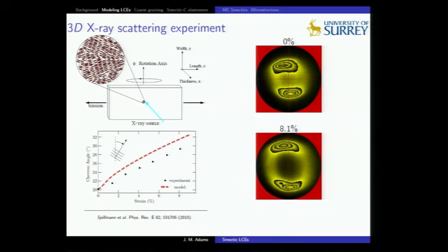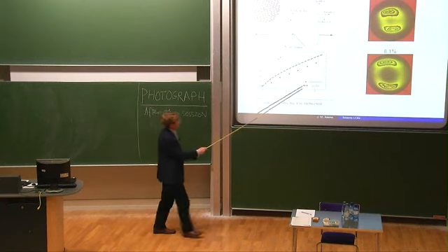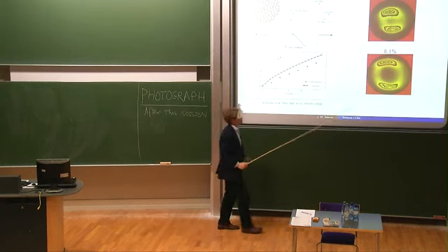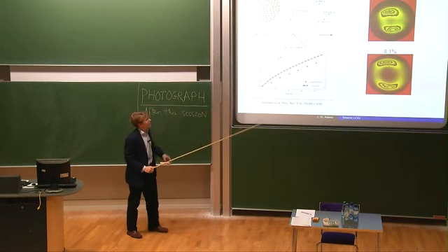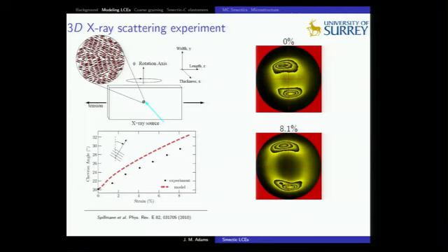What they've done is measure the X-ray scattering pattern of this material by shining an X-ray source here and then rotating the sample around this axis phi, which means you can collect X-ray data from a whole range of different directions and find out what happens to the X-ray scattering that I mentioned at the start of the talk. So there's some loss in intensity of the Smectic layers. These plots show looking down on the top of the scattering pattern that I showed earlier, so they'd be in the plane perpendicular to the board.